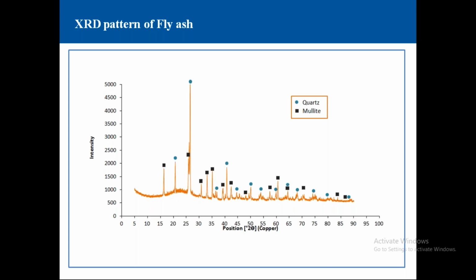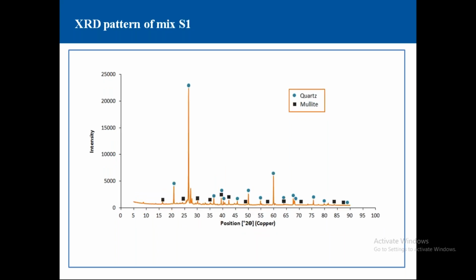X-rays are diffracted differently by each mineral based on the atoms present and their arrangement in the crystal lattice of the mineral. If you look at the fly ash X-ray pattern in its normal state, it's mainly composed of amorphous and crystalline substances such as quartz and mullite. There are numerous peaks of mullite and quartz in the crystalline phase. The highest intensities of quartz and mullite peaks were found at 5000 CPS and 1804 CPS and were indexed at 26.6 and 40.72 degrees.